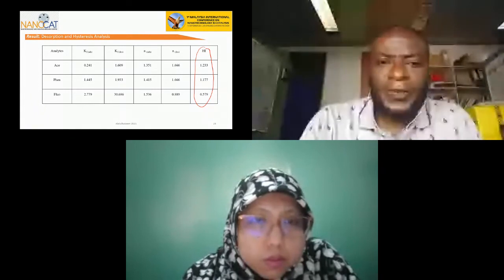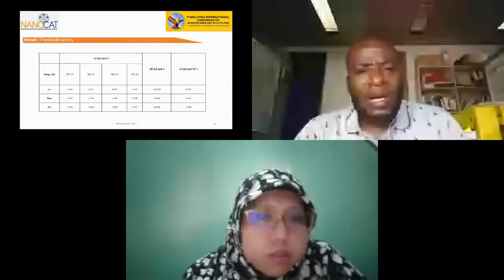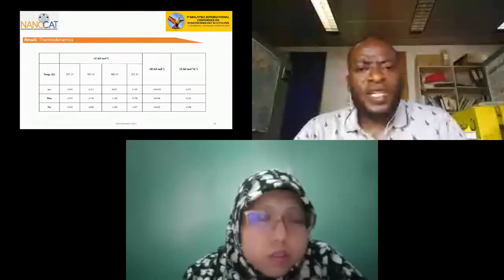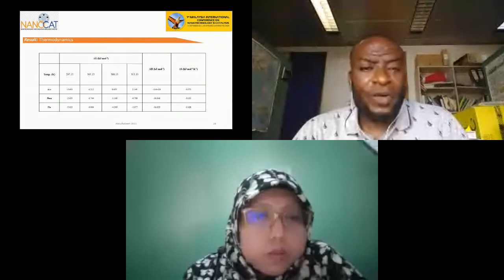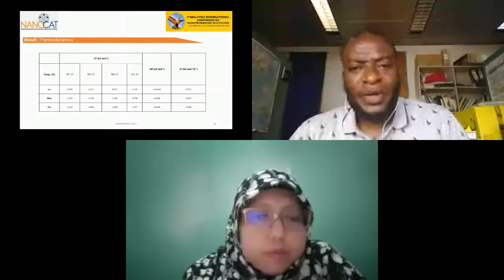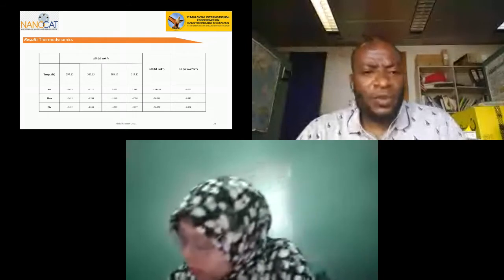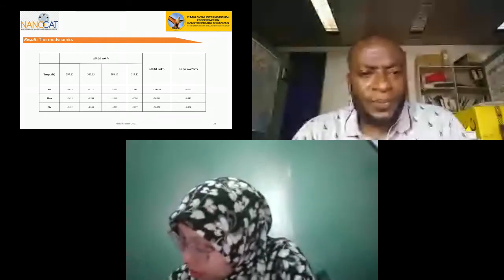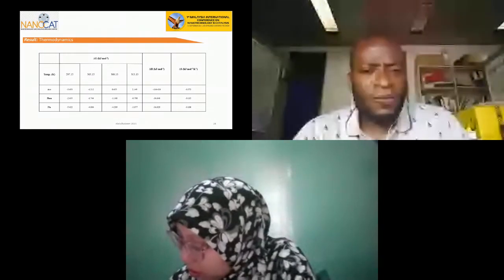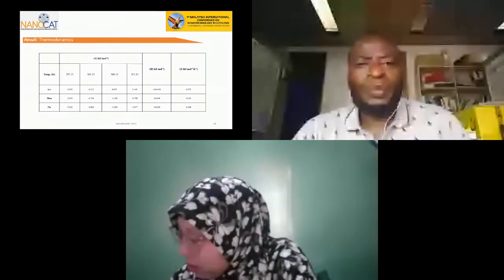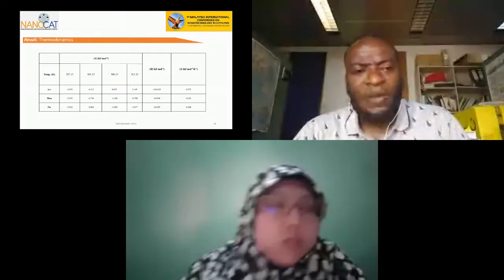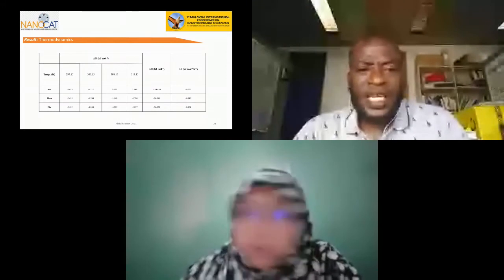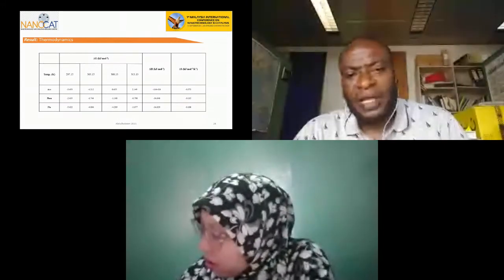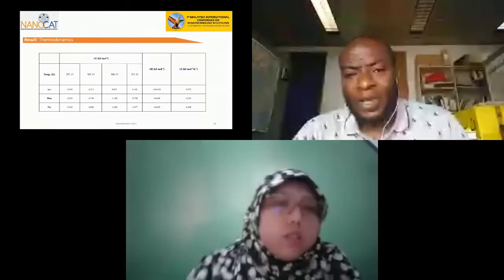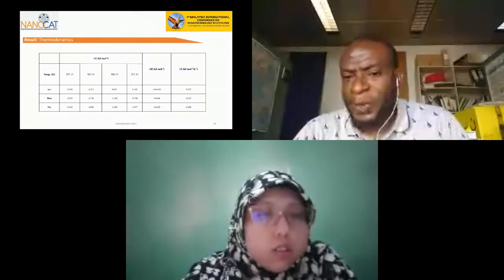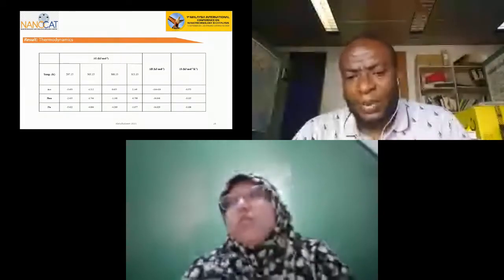this study. And from a thermodynamic point of view, we vary the temperature to see the thermodynamic behavior of this adsorption. And we discovered that delta G were all negative for phenanthrene and fluoranthene, which shows that they were all spontaneous at these different temperatures. However, for naphthalene, it was negative at lower temperature and it became positive at higher temperature, which shows that it is spontaneous at lower temperature and non-spontaneous at higher temperature.